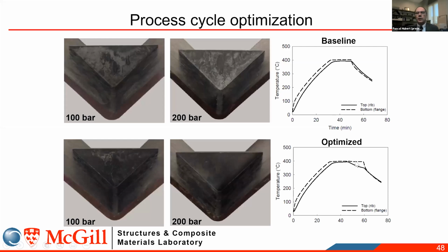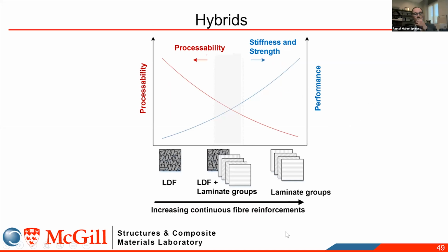Now, what you see here is that by just delaying the cooling down of the bottom part compared to the top part, you end up with maintaining this pressure and creating a very nice surface for the rib. So through this development of better process control and simulation aids, you can really now make these net shape parts. Now, one interesting thing that you can do with these net shape parts is to also combine with your short fibers, or long discontinuous fiber, elements using continuous reinforcement that you can place strategically. And that in general will help and increase the performance and reduce some of the variability that we see with these materials.